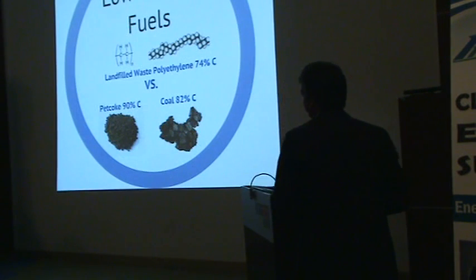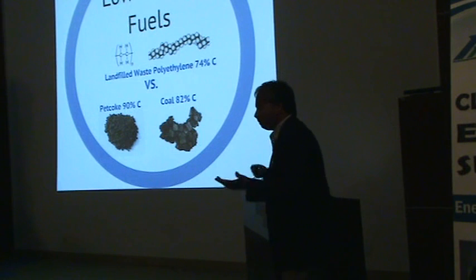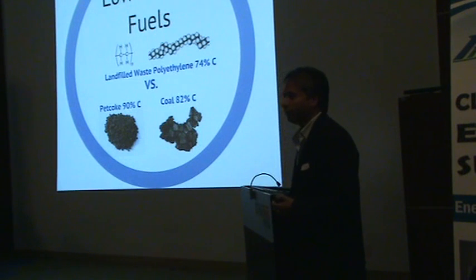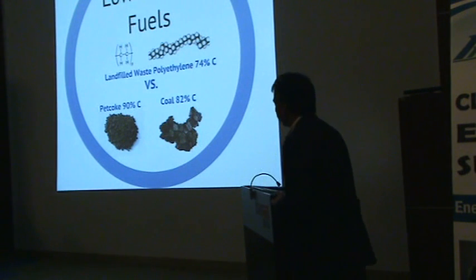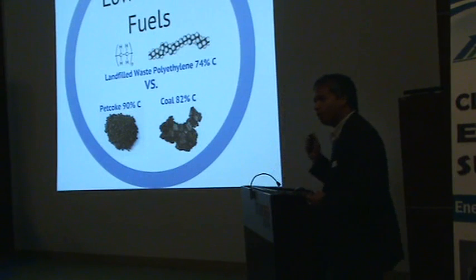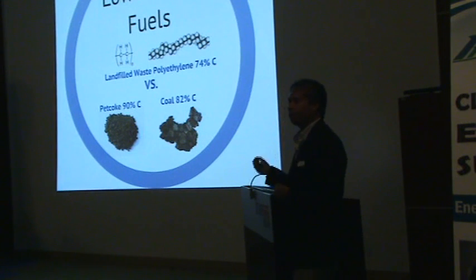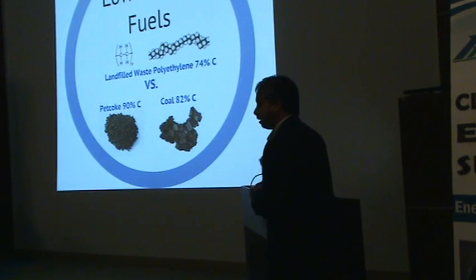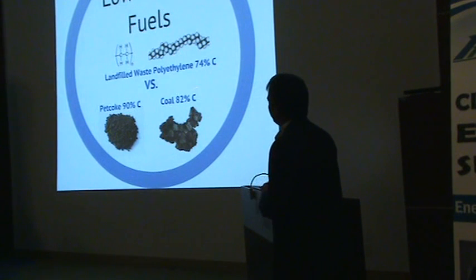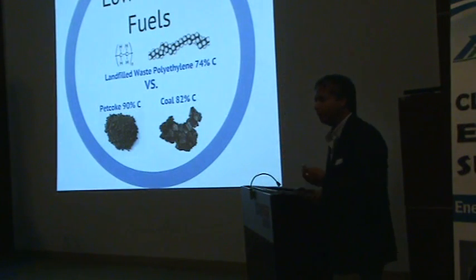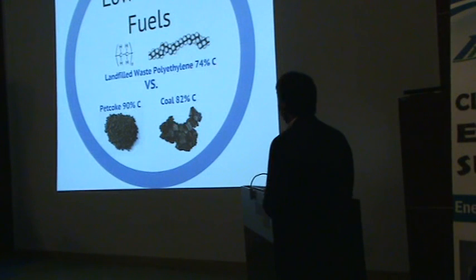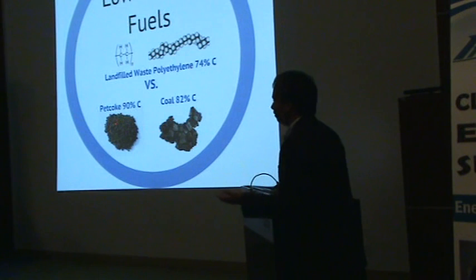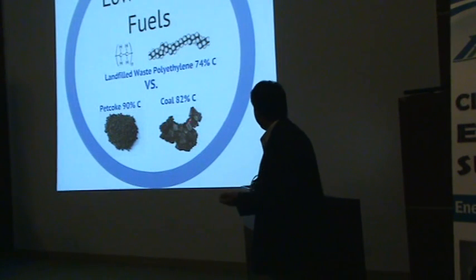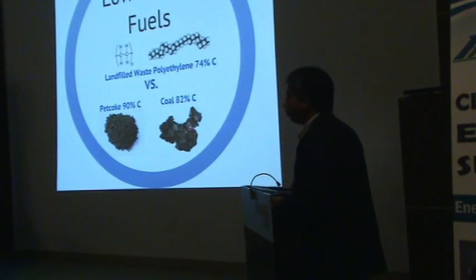Low carbon fuels, utilizing things like plastic bags. We did a trial at our St. Mary's, Ontario plant. At the temperatures we're burning at, over 1400 degrees Celsius, it thermally destroys any organic molecule. There's absolutely absence of any harmful, toxic organic molecules. And so these things that would otherwise be sent to landfill and waste can be utilized as a fuel that is actually much more highly refined than things like petroleum coke, which is bottom of the barrel, literally, and 82% carbon coal.